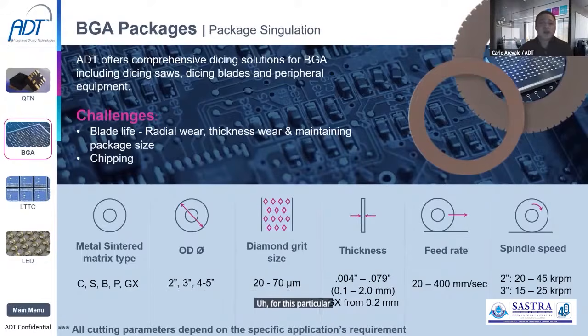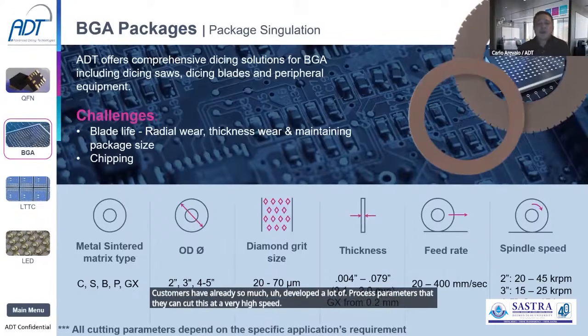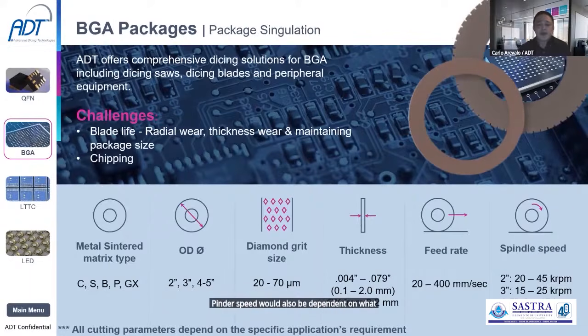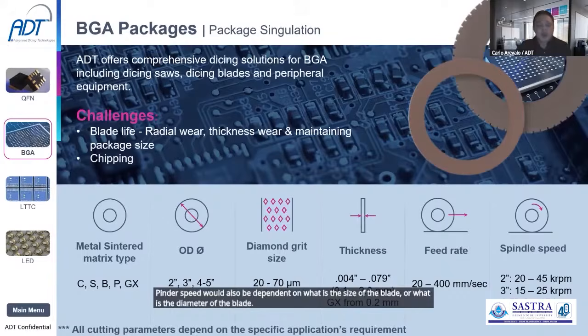For this particular application of BGA packages, ADT has a few models also, but it's mainly concentrated on the metal sintered blade. The OD can range from all sizes, from 2, 3, 4, and 5. Diamond grit size from 20 to 70. Thickness range of 100 to as thick as 2 mm is also available. Feed rate can go as high as 400 millimeter per second. Customers have already developed a lot of process parameters so that they can cut this at a very high speed. Spindle speed would also be dependent on the size of the blade and the equipment that you are using.